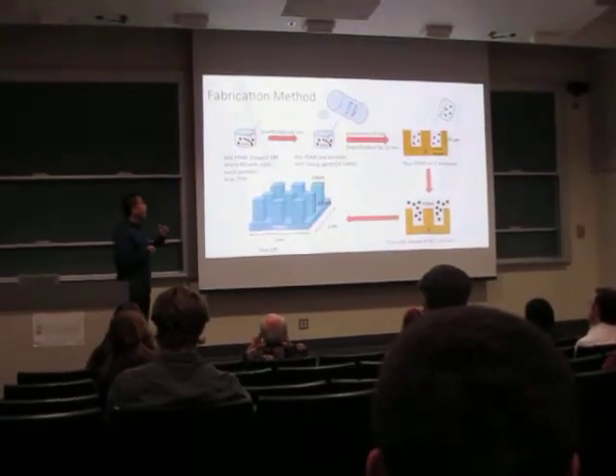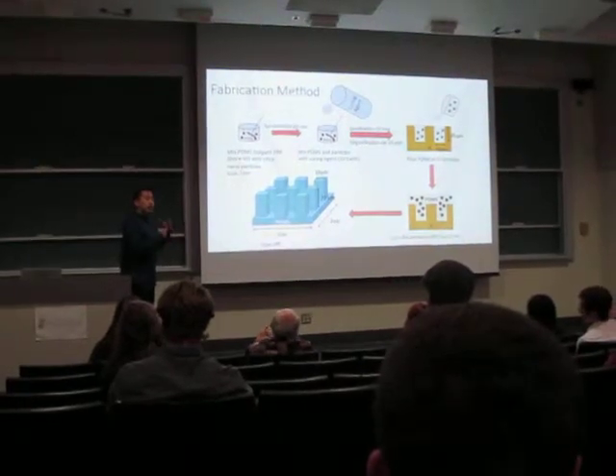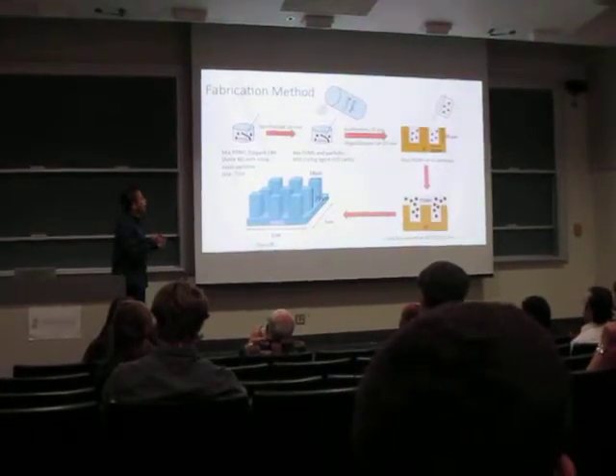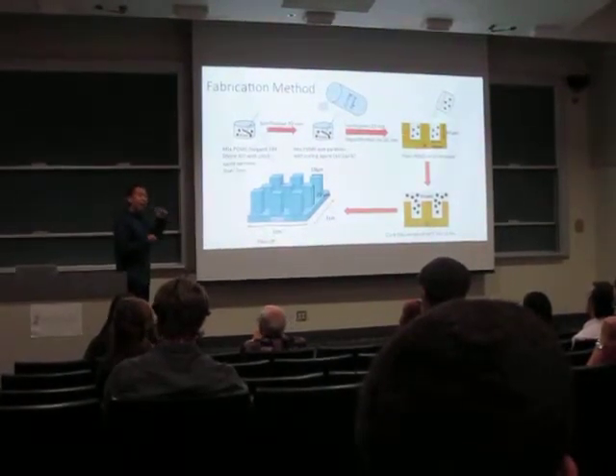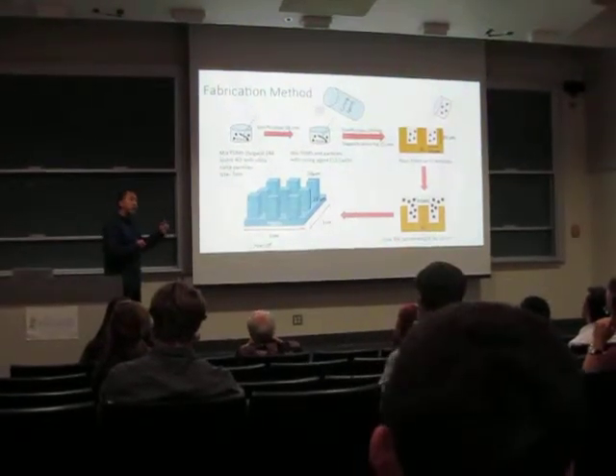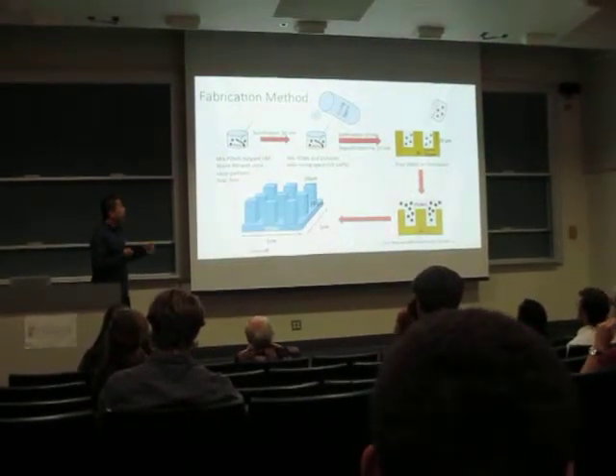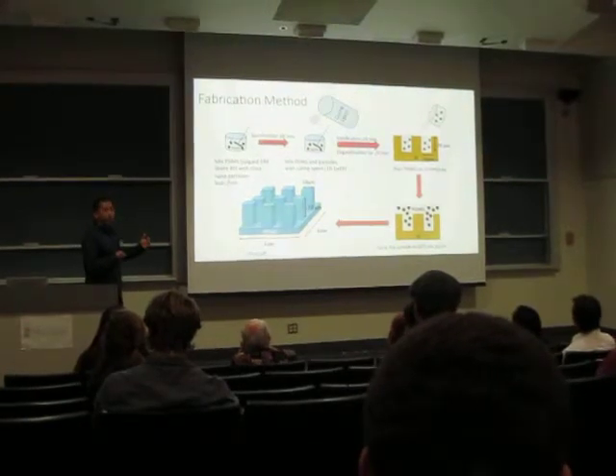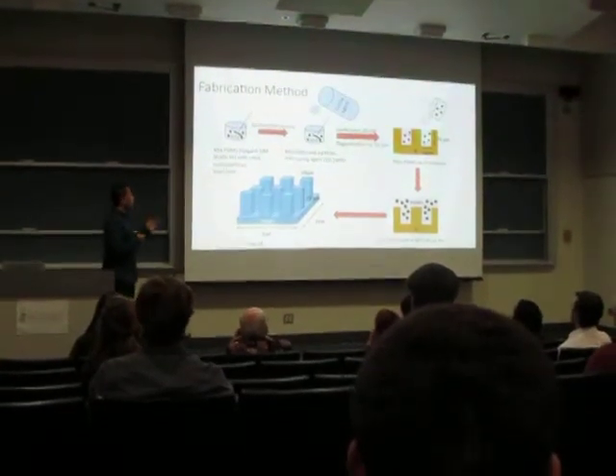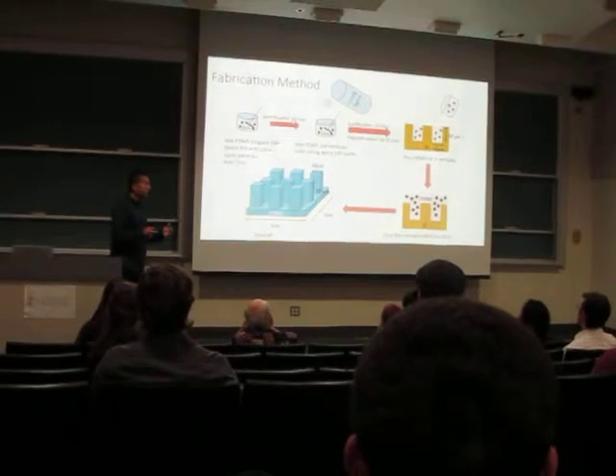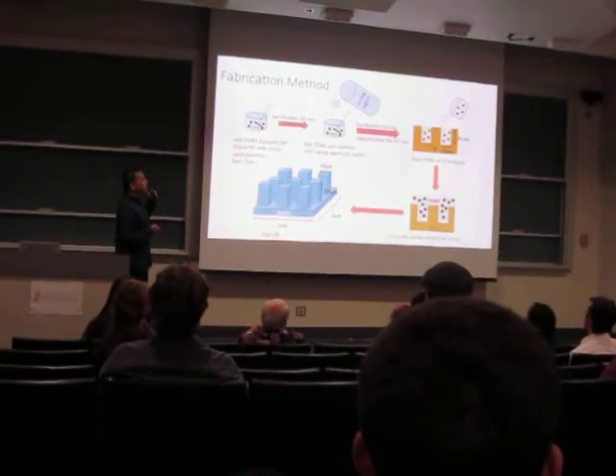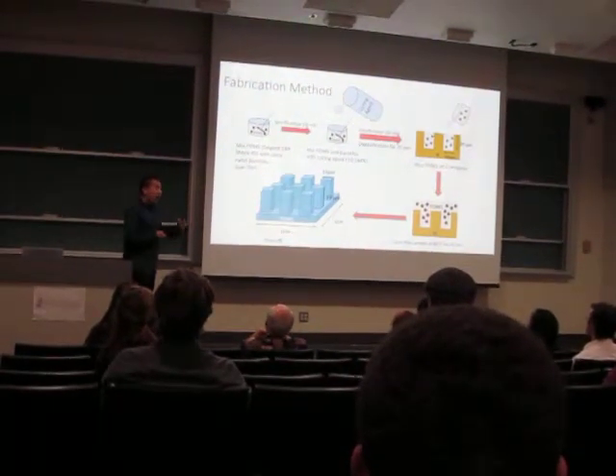Then we mix with the curing agent. This is the step where we can play around, since it depends on how much curing agent we add, and that can change the strength of the material. We sonicate for another 20 minutes to make sure both the particles and the curing agent are well dispersed. And we want to make sure there is no gas trapped in the sample.